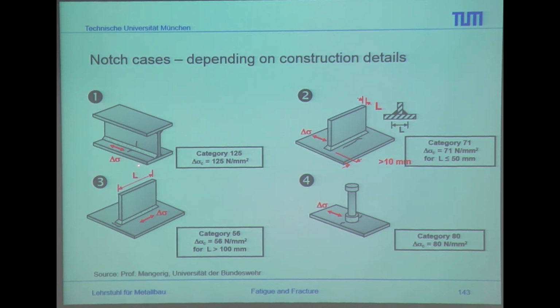And so the nominal stress concept gives you at this part the stress range which can be handled at 2 times 10^6 cycles. So, for example, for a welded seam which is longitudinal to the stresses, you can handle here 125 MPa. For an appended plate, you can handle around 56 MPa, but also, as you can see here, this stress is related to the length of the appendix. So, for example, if you change the size of the appendix, also the detail will change. And the same for this part. As you can see here, for L smaller than 50, you have 71. For L larger than 100, you have 56.